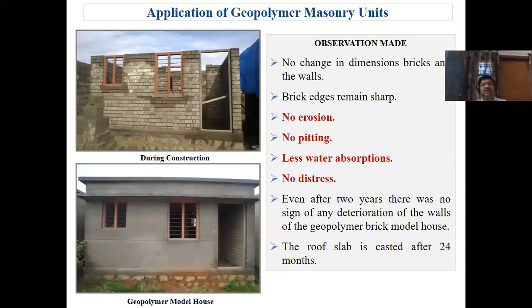See here, no change in dimension of the brick walls after 2 years. Brick edges sharp, no erosion, no pitting. Of course, very less water absorption, no distress, right? Even after 2 years, there was no sign of any deterioration of the walls of the geopolymer.